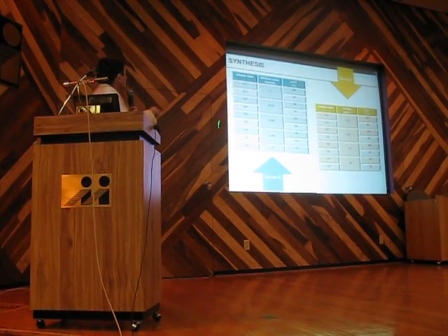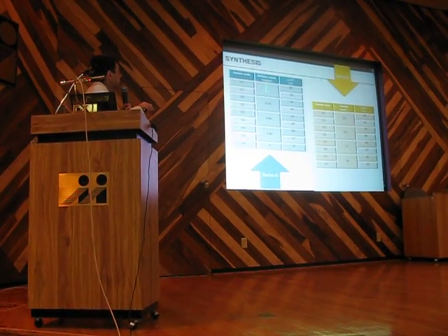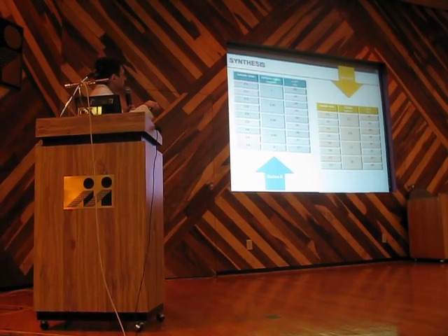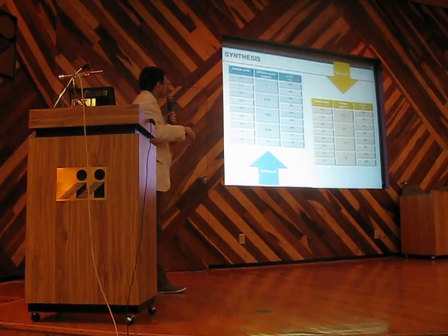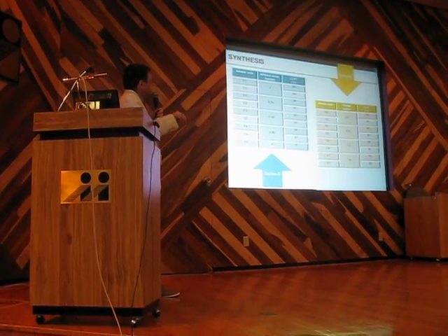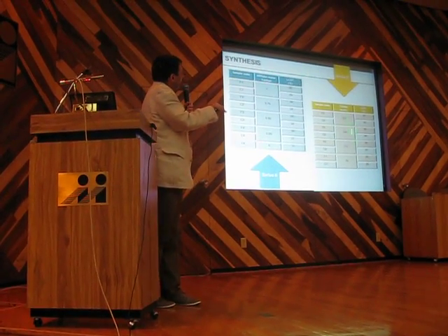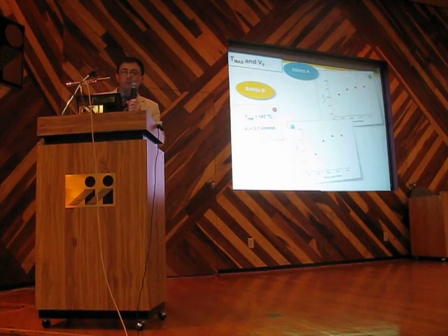Okay, we performed a series of syntheses by varying the ratio between the two monomers, from 1 to 0 NIPAM molar fraction, and by keeping constant the 1-to-1 ratio between the monomers while varying the amount of crosslinker.